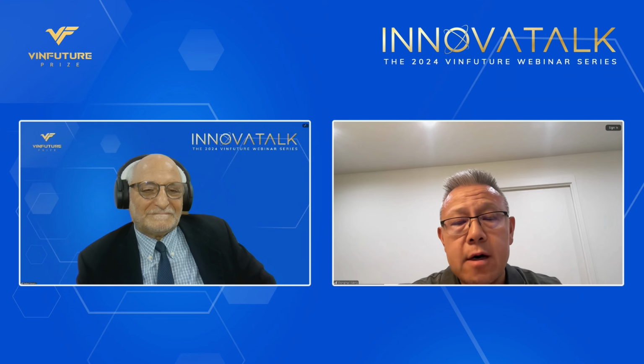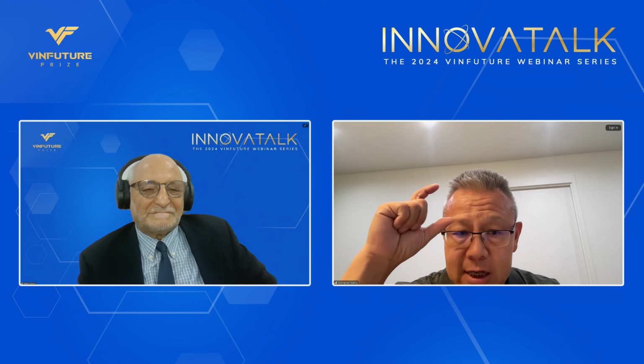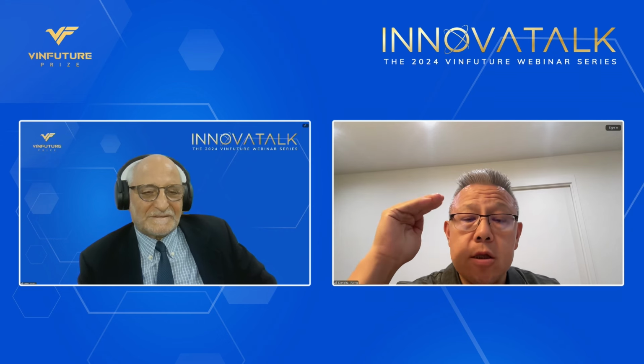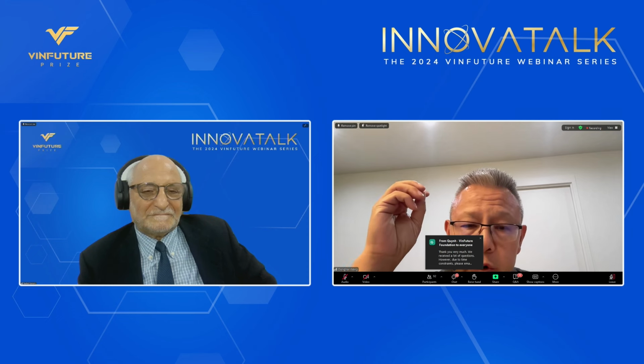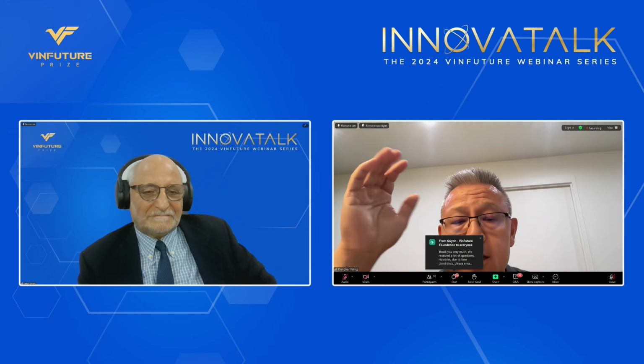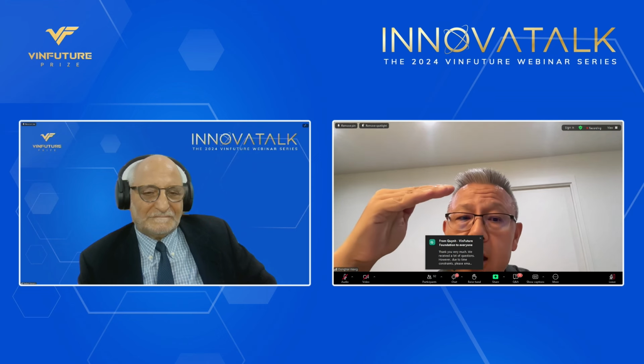So when you have high energy density lithium ion, for example, 250 watt-hour per kilogram, you need to have a certain thickness. So it's not just the transport at the surface or absorption at the surface. It's also about this kinetics across a very thick electrode.